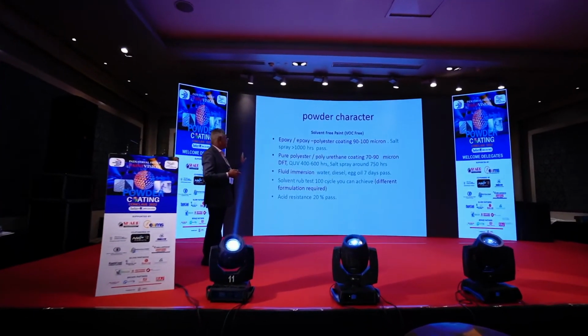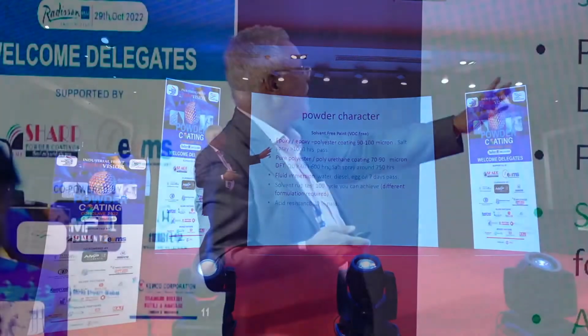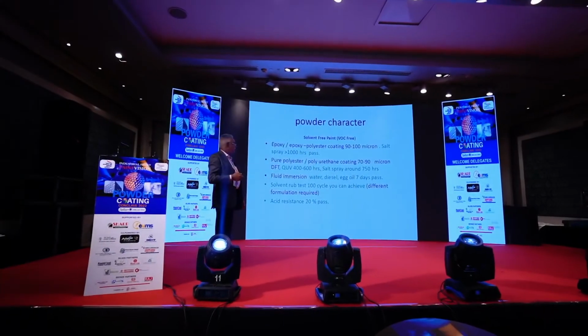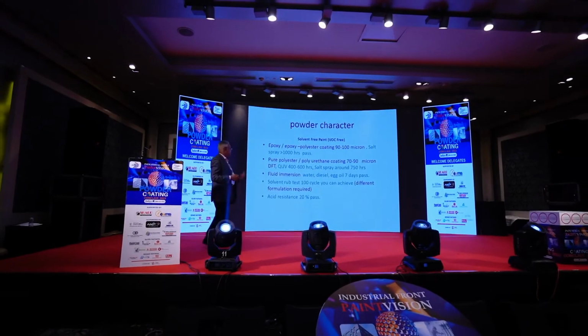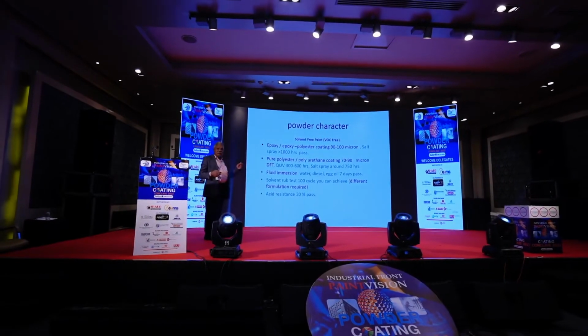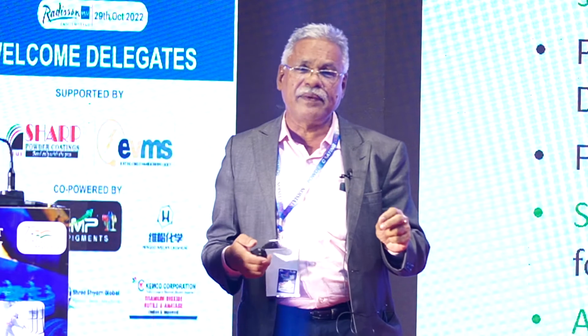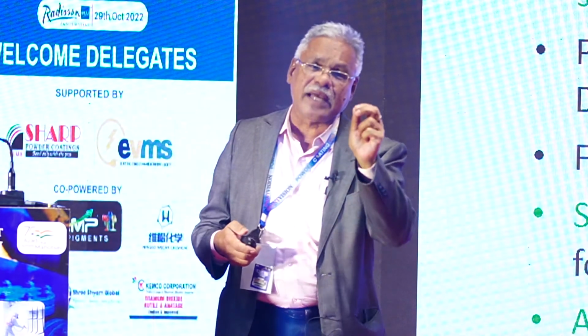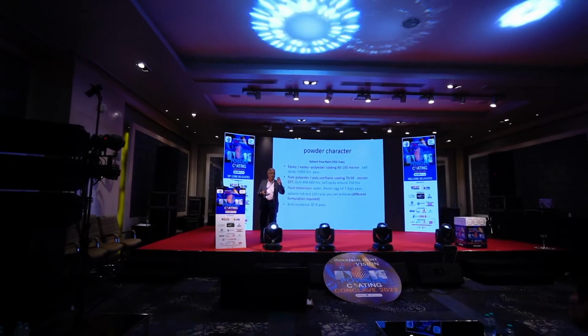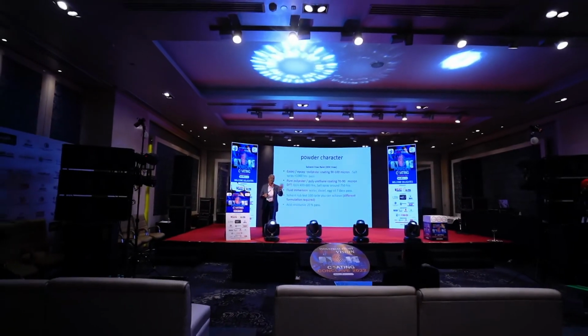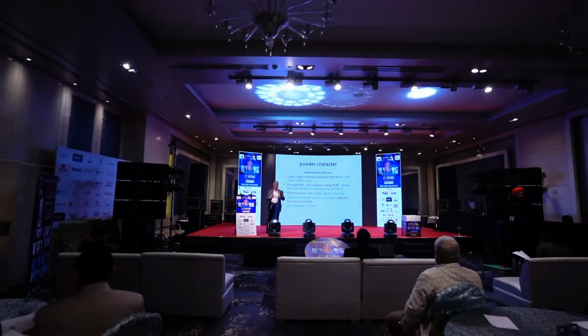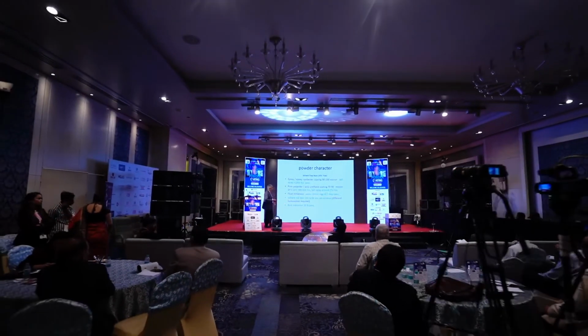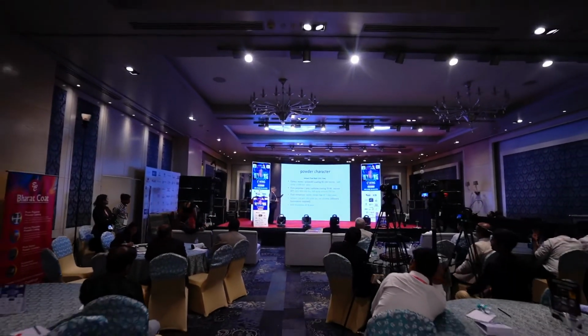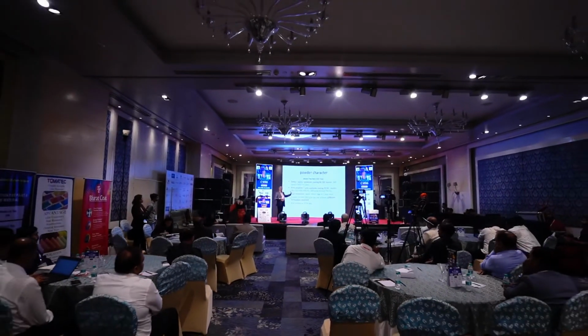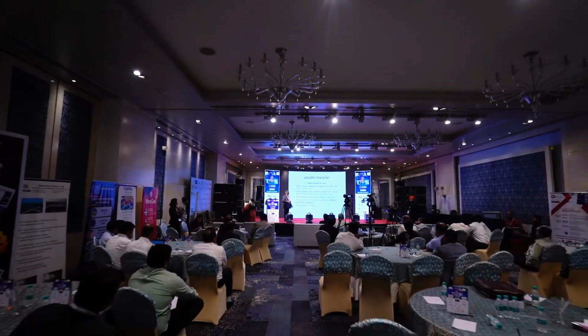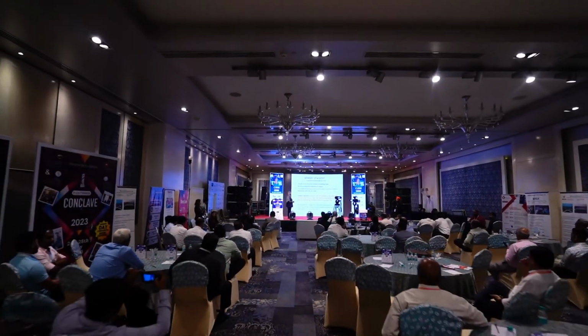Then fluid immersion test, water, diesel, engine oil, 7 days it will pass. All systems will pass. Then solvent rub test, 100 cycle it will pass. But you have to ask the resin manufacturer, but solvent traps की कितना चाहिए आपको? 100 cycle चाहिए, 50 cycle, all polyester will not pass. So you have to specify those things and get those type of resins. Acid resistance, generally it will pass, epoxy and epoxy hybrid system around 20%.